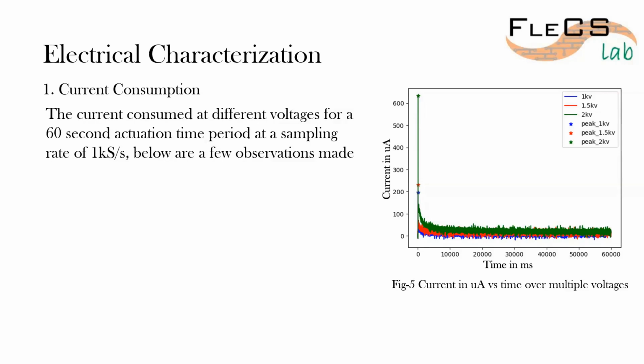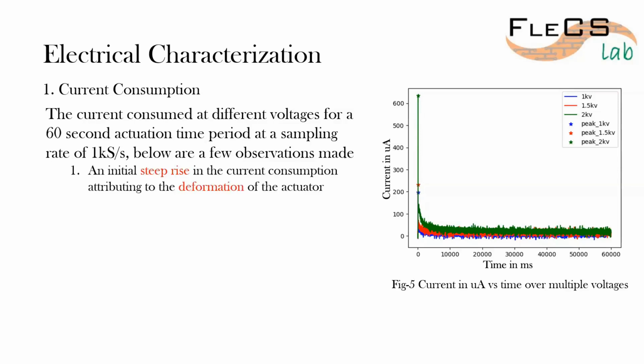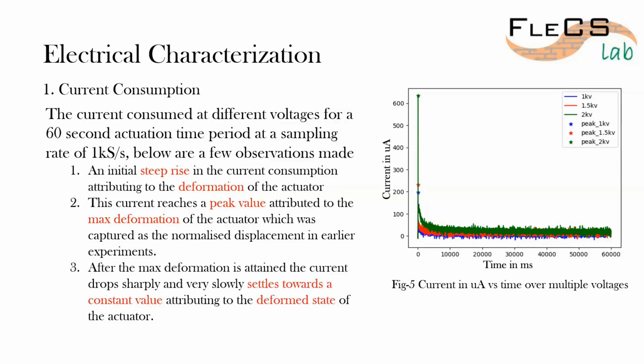When you give it a voltage, it charges. It takes a lot of current, charges up, and then settles down. Where it settles down, and where this peak is, are both interesting. Where it settles down will give you the leakage current, a constant leakage current or leakage resistance of the entire capacitor. So that is also interesting in some cases. And the integration under the curve for the entire thing will give you the charge, which basically gives you the energy that it consumes. So both of these things we have analyzed as well.